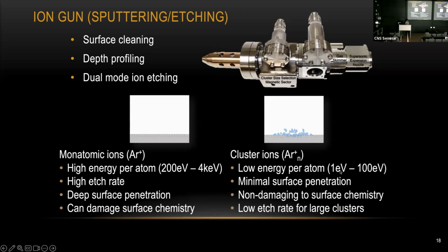You can see, for each atom, the energy is only between 1 to 100 eV. But for monatomic, it's much higher. It can go all the way up to 4,000 eV in our lab. So it can give you a much higher etch rate, and you can etch much deeper, but it can also damage